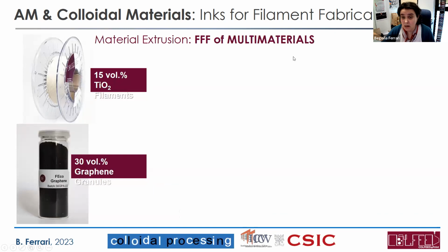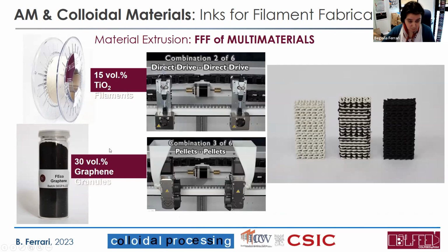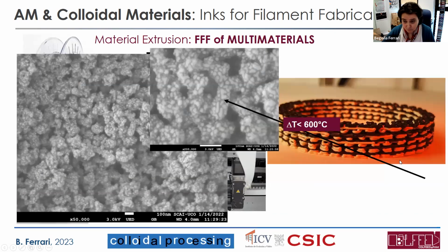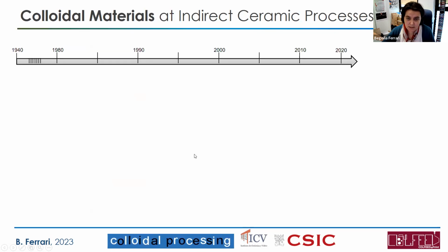And also we can manage and print multi-material. We can mix, for example, titanium and graphene here, you can see, and we can achieve this kind of structure inside of the filament, right? So mixing titanium and carbon inside of our sintered material, right? So this is also something to explore right now.